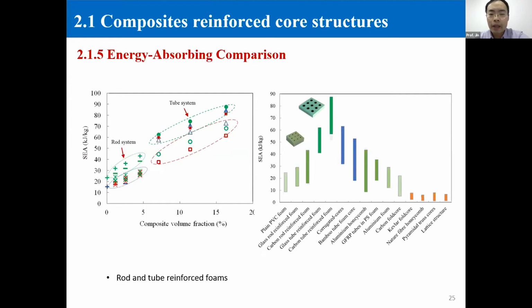And finally, we compared the rod reinforced foam and the tube reinforced foam with other structures. And we found the SEA is over 90 kilojoule per kilogram. The energy absorption is much higher than other sandwich core structures.